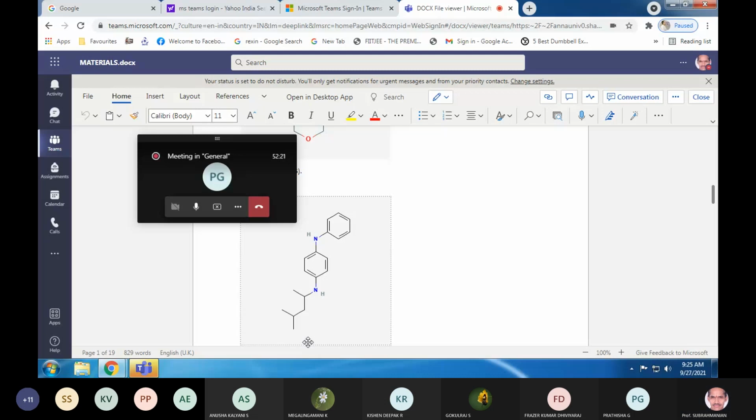In order to protect the unsaturation so that the rubber is able to maintain its large recoverable deformation, the choice of anti-degradant is one thing, and the order of addition is another. If you follow the conventional order of addition, we may end up with poor scorch safety.